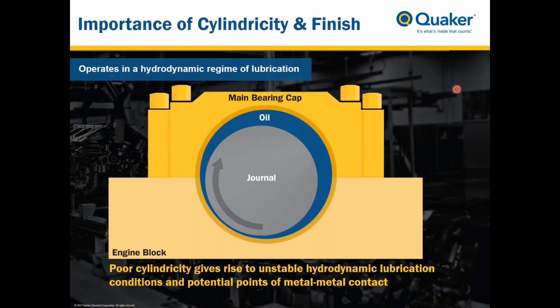And really the thinness of this film demonstrates how critical it is to have very good tolerances on your cylindricity. Because a loss of cylindricity of the actual reamed bore would subsequently result in a little bit of loss of cylindricity when the bearings are installed, and it could give rise to a very unstable condition of hydrodynamic lubrication, which could lead eventually to more accelerated wear of the bearings, and probably before that, a very noisy operation of your engine.